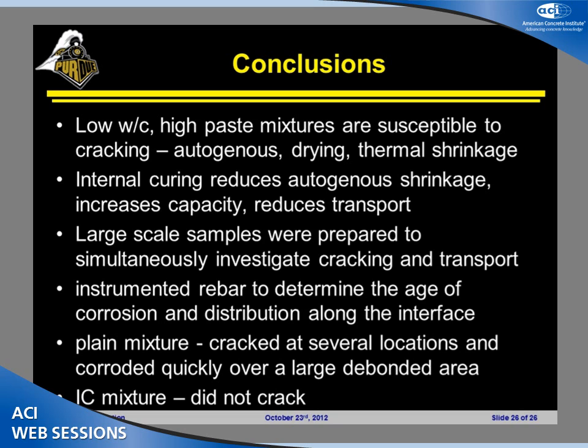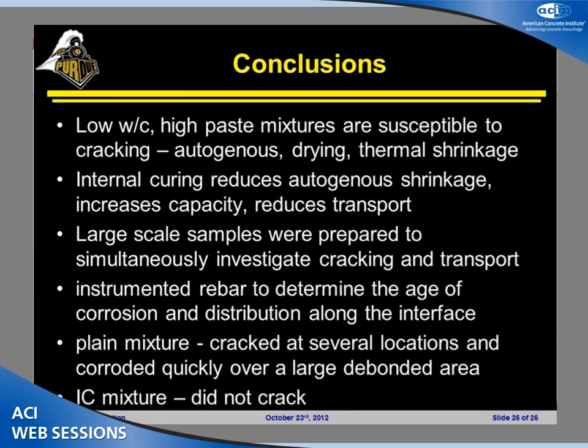That was going to be my second question. How much is the debonding with respect to the diameter of the bar or whatever? Yeah, well, in this case, it's a small sample that we're looking at, because you may or may not realize drilling out those bars and placing those in, that's not something we're going to be doing on a lot of bridge decks because it takes a little bit of time. But almost every time we see at least 4 to 6 inches at minimum, and even more coming back away along the bar. But it also depends on the load. If the stresses are staying low, it's possible that the crack just goes to the bar, slight debonding. But in the case we were looking at, there's a lot more debonding taking place.